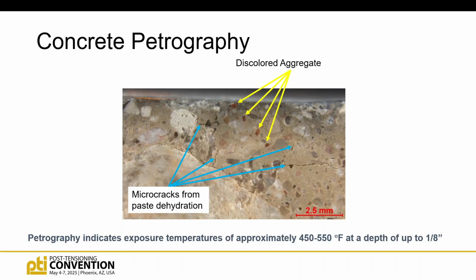So I mentioned concrete petrography. Our guys are really good at looking for these changes in colors in the aggregates. So the orange color, they call it pinking in the petrography industry. The paste will begin to pink, the aggregates will turn orange or almost rust colored. There'll be lots of micro cracks and fissures in the concrete because as the concrete heats up, it's actually cooking the moisture out of it, and it causes it to crack and fracture. And from that, they can deduce the depth of impact of the heat on the concrete. And you can see we're zoomed in pretty close here at 2.5 millimeters.